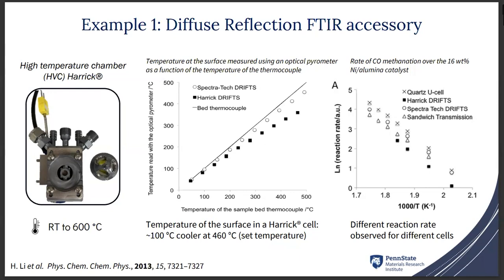And it was said, or pointed out in the literature, that there is a drift of temperature between the temperature recorded at the sample bed thermocouple and the actual temperature on the sample. So this temperature drift can be up to 100 degrees Celsius at a 460 degree Celsius set point.